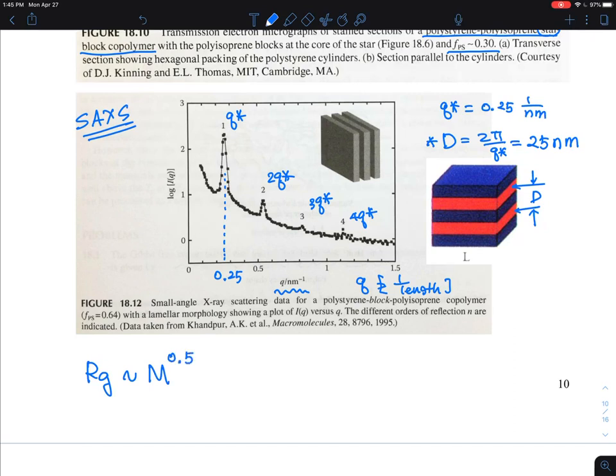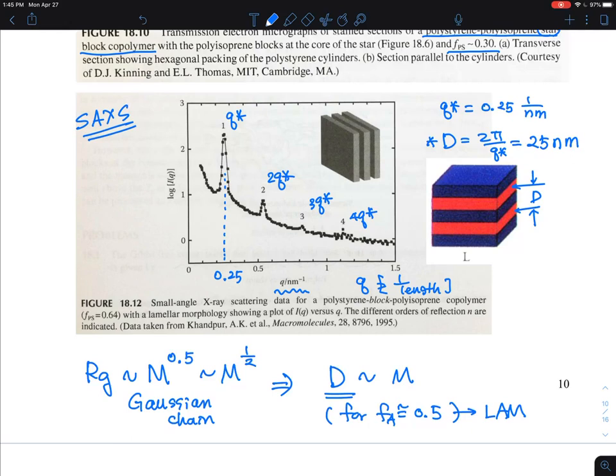Remember the radius of gyration scales with molecular weight to the 0.5 for a Gaussian chain. Block copolymer people measure how the domain spacing scales with molecular weight for symmetric polymers. From the lamellar phase, this domain spacing scales as M to the 0.67.